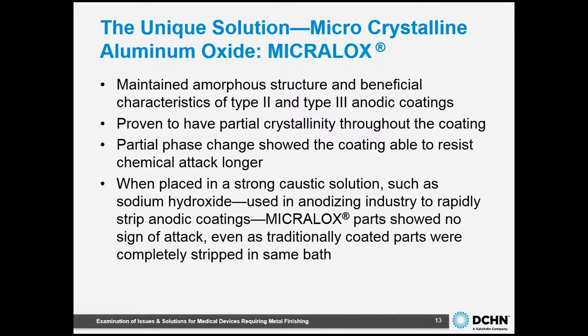So what you just saw is a new patented technology that we call MICRALOX. It is the new standard of anodic coating for reusable medical devices. Through XRD analysis, we were able to prove the existence of partial crystallinity throughout the coating, thereby significantly increasing the resistance to chemical dissolution, but still maintaining the most beneficial aspects of traditional anodize. This partial phase change did the job. When subjected to high and low pH chemistry, there's a very significant difference in performance over both type 2 and type 3 conventional coatings.